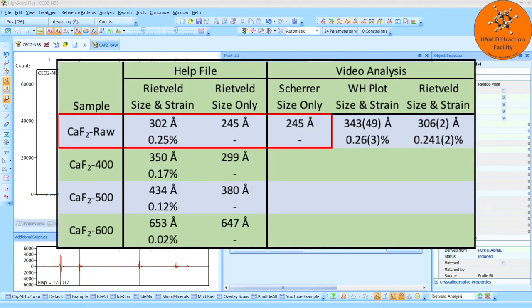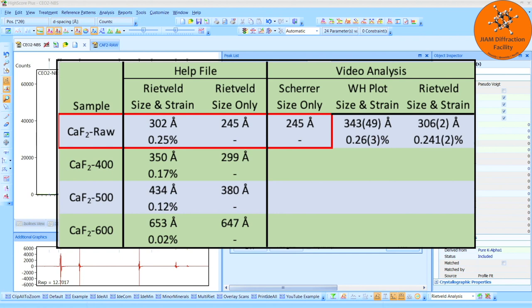Here we see a comparison of results. The first column is the sample name, the second and third columns show you the results provided by Panalytical's help file, and the last three columns are the results that you will see in this series of videos. If we compare the third and fourth columns, we see that they match very nicely. However, the results are quite a bit lower than the rest of the columns that account for microstrain, and this shows you the effect of ignoring microstrain for a sample that has microstrain.